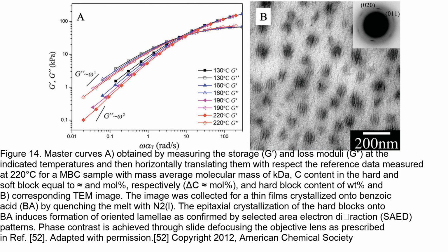The corresponding TEM image shows the epitaxial crystallization of the hard blocks onto benzoic acid, BA, resulting in the formation of oriented lamellae. The crystalline lamellae are stacked with the normal parallel to a common direction. This confirms the microphase separation in the solid-state morphology and the formation of a microphase-separated morphology reminiscent of the melt